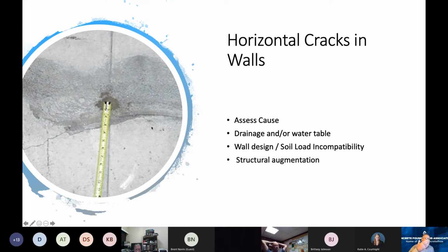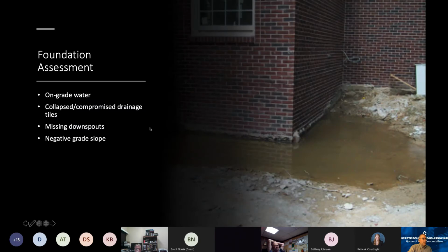The horizontal cracks, go back to the drawing about the soil loads. This is where the horizontal cracks develop, from a breakdown in the design of the wall versus the construction of the wall. And most of these, in my opinion, occur from means and methods problems, where the builder didn't allow the wall to be braced before backfilling. The backfilling wasn't done in lifts. They used a bulldozer and drove the bulldozer along the side of the wall and put an excessive pressure on the wall that began to fold it, or put pressure more than what the vertical reinforcement and the modulus of rupture could substantiate. And so a lot of times structural augmentation is going to be needed.